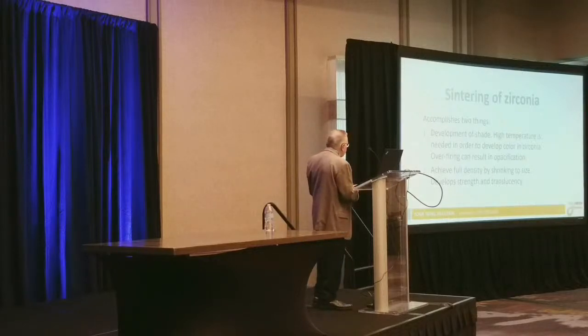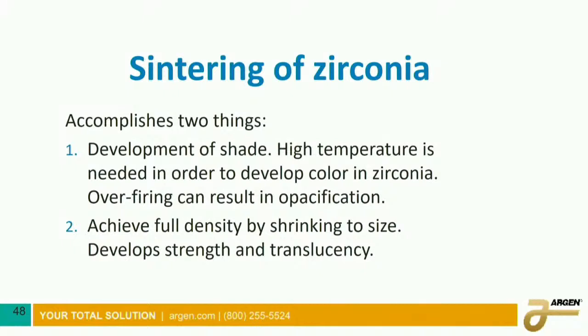Okay, so on sintering, we're trying to do two things. Number one, the development of shade. As you know, when you look at those discs, regardless of what shade it says on the side, they all look the same. The reason for that is that the color is only developed at high temperatures, over 1100 degrees C. Overfiring some of these newer materials, however, as I mentioned, could result in opacification. So we have to be careful as to what temperature we're going to be sintering at. And also, of course, we're trying to achieve full density by shrinking to size.